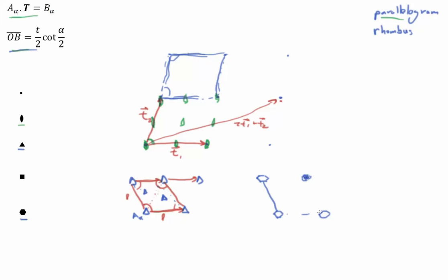In this case, this original rotation axis here can be translated over to a new rotation axis, but then it is rotated up by pi over 3 radians, rotated over here, rotated here, and a combination of that sixfold and those translation vectors can fill up all space, and again we're going to see this 120 degree rhombus. However, there are additional rotation axes. This sixfold is going to map onto this sixfold, so we already see that one, but remember a sixfold rotation axis also contains within it a threefold rotation axis and a twofold rotation axis. When you work with those, you're going to see that we have twofold rotation axes along the bisectors between these sixfold rotation axes and along this one.